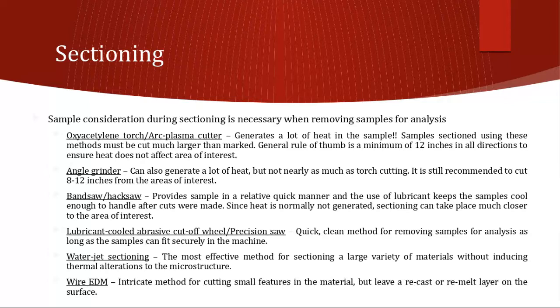So in order to use this technique successfully, the general rule of thumb is to cut 12 inches in all directions from the point of interest that you're looking at, so that the heat doesn't affect that specific area. So when I mentioned a 2-foot sample, if the area of interest is right in the middle, 12 inches on each side gives me a 2-foot sample.